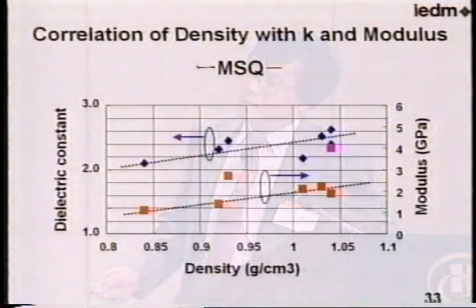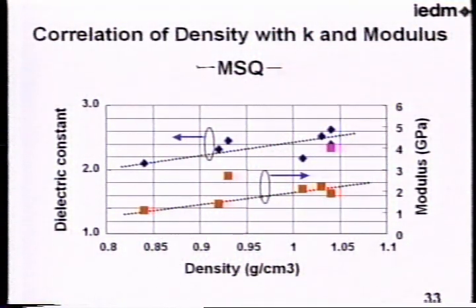And also, there is some correlation between the dielectric constant and also modulus with the density of the film. In this case, all the samples are MSQ. MSQ is as indicated in the table. This is some carbon-doped SiO2 that is formed by SOD. There is a good relation between the dielectric constant, density, and also modulus, like this.